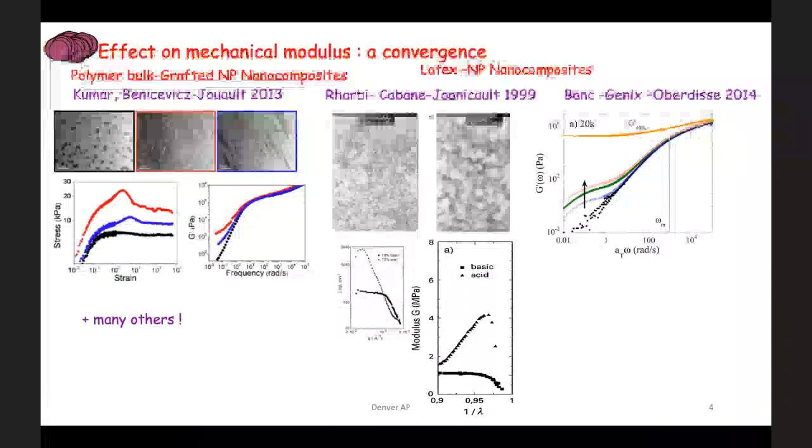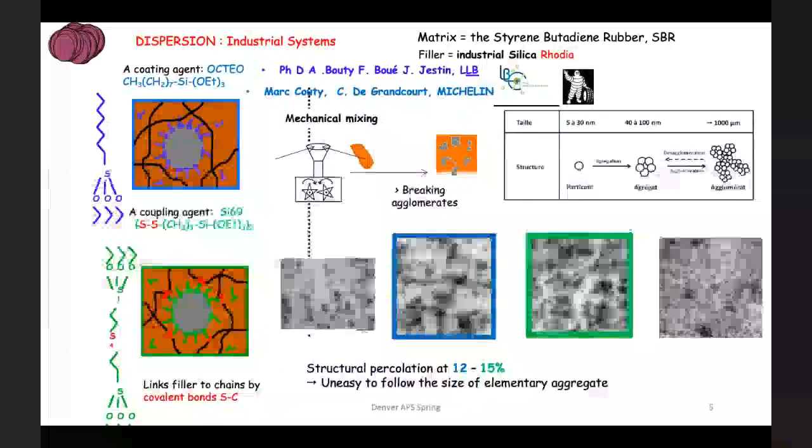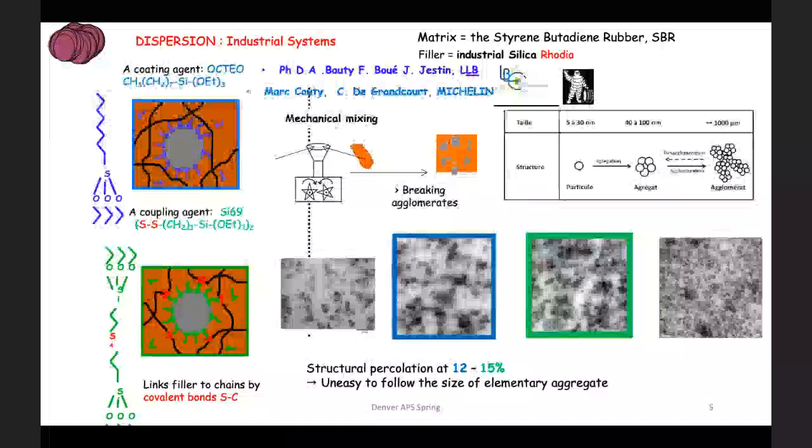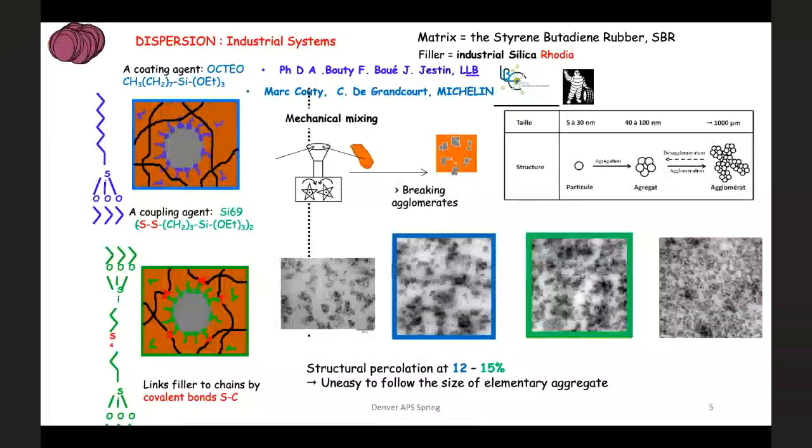Thanks. Thank you. I have to go back and read that, but that's pretty interesting for us. Yeah. So actually, in the case of Julian, the trick was that they mixed some normal latex nanoparticles and some deuterated latex particles. So at the beginning, the chains were not mixed, and they had to wait a certain time until the polymer chains diffuse. Actually, I see Guillaume Daiza in the attendees, so he can explain it better if he likes.